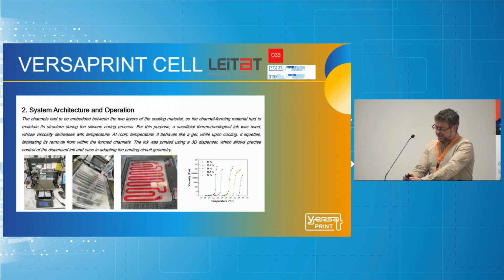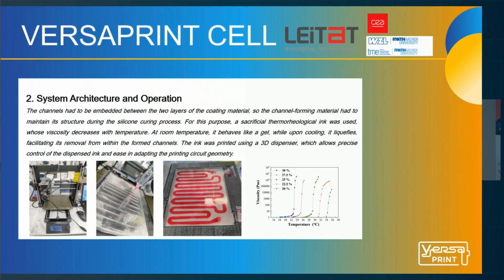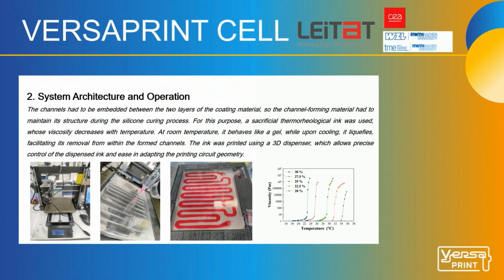Here I explain briefly the process for the 3D printing of the channels. The configuration of the channels has to be embedded between the two layers of the coating material. The ink that is printed for the circuit has to maintain this structure during the silicone curing process. For this purpose, we selected a sacrificial thermorheological ink, whose viscosity decreases with temperature.